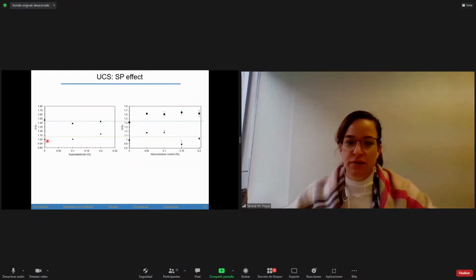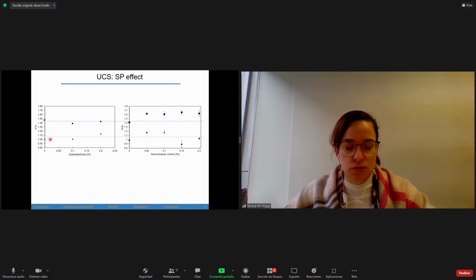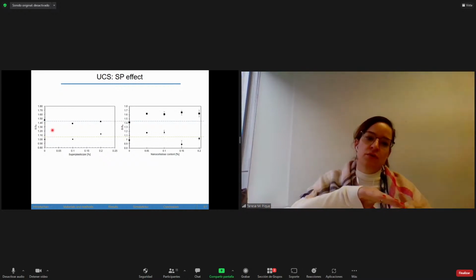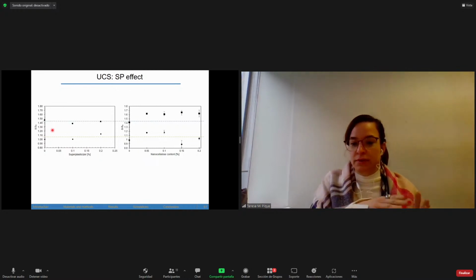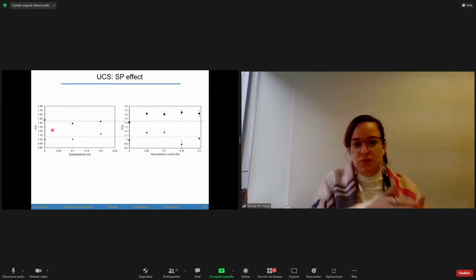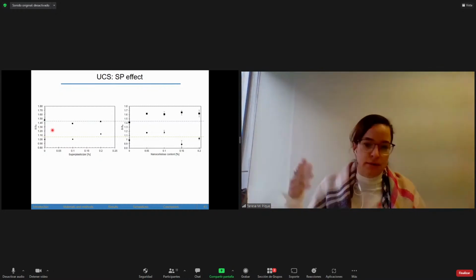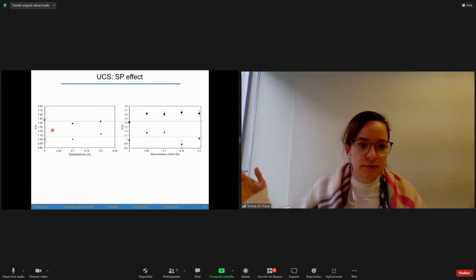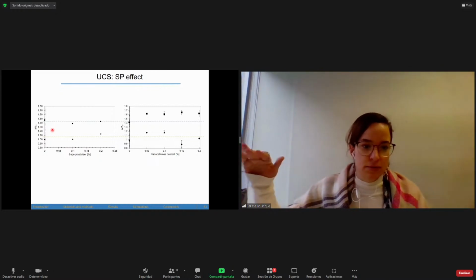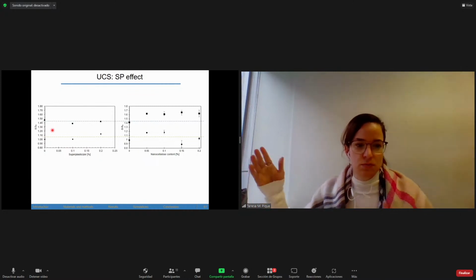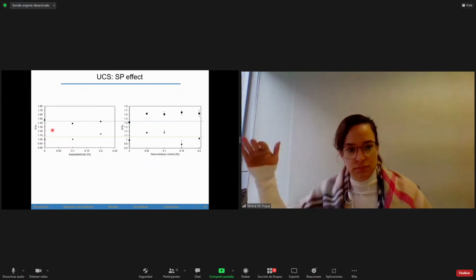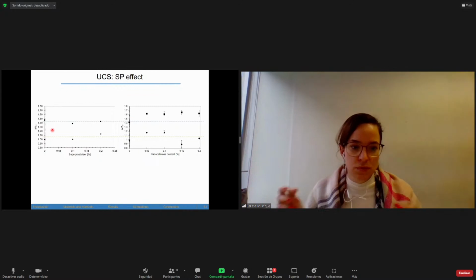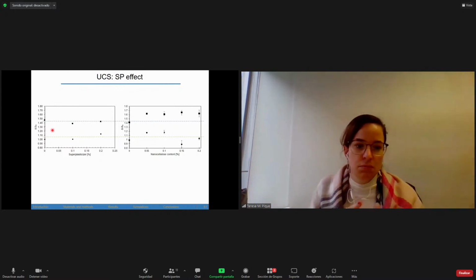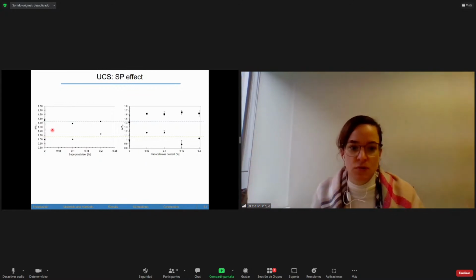Yeah, but at 7 days there are different mechanisms happening, so maybe it's not the best one to use to compare. I mean, cement curing is very unstable and changing a lot from 0 to 28. Unless you have supernormal activity or whatever, it usually stabilizes at 28. So you should use those stable ages to compare, because maybe at 7 there are different things going on.